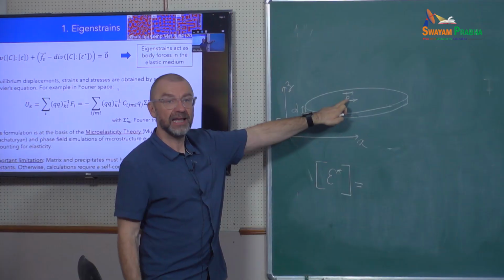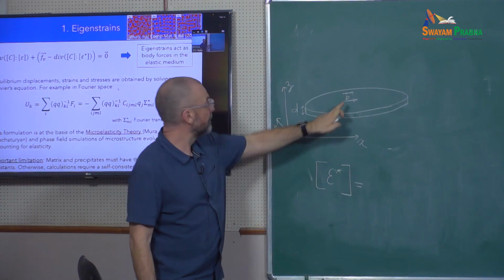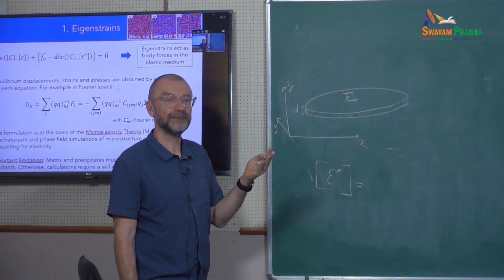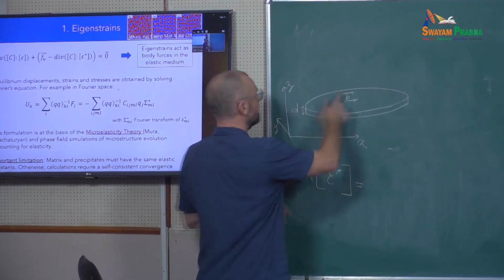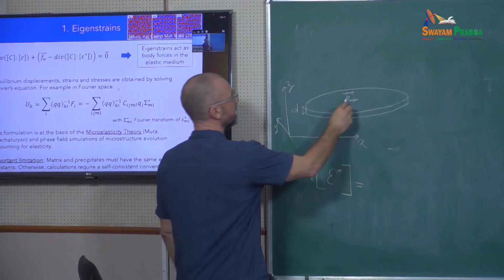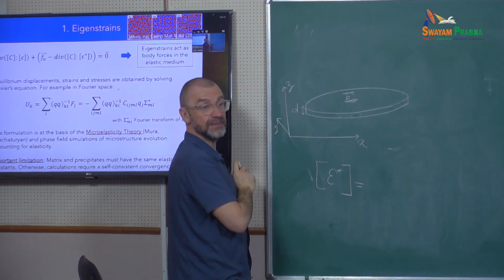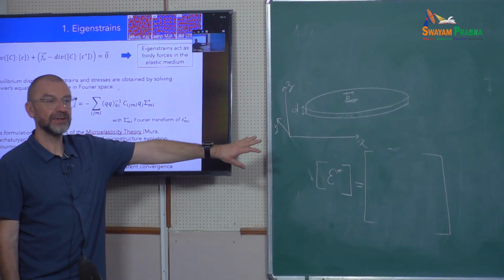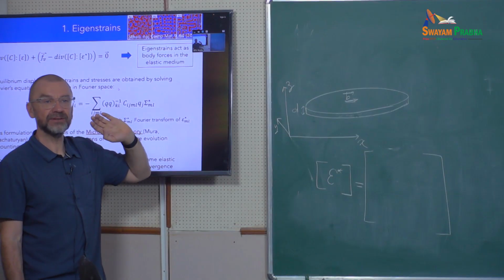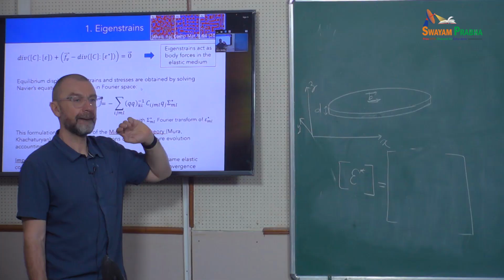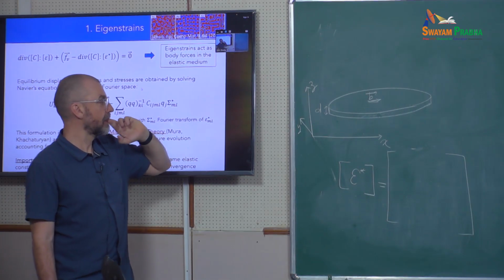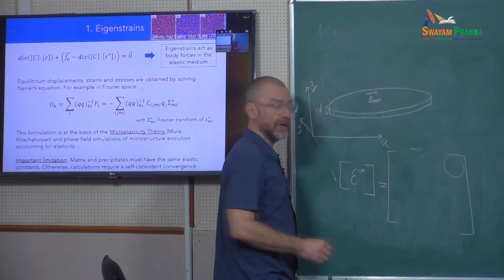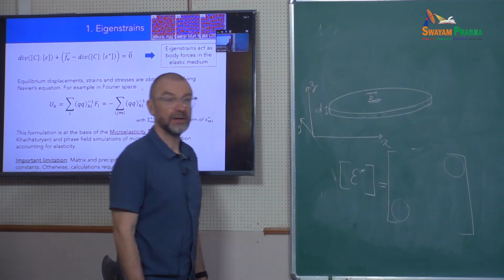It wants to have a shift of B from one side to the other of the platelet. What kind of deformation is that? It's a shear, right? So if I'm using these axes here, and I assume that B is in that XZ plane, which component of the deformation tensor would correspond to that shear? It's XZ, right? So it would be this term here, and by symmetry we also have that term there.